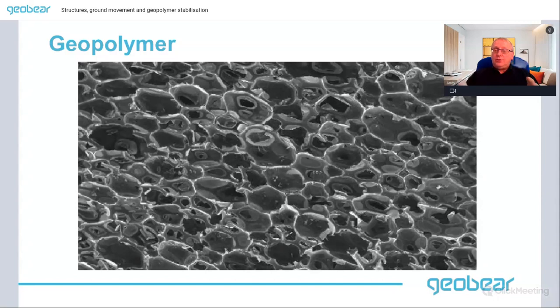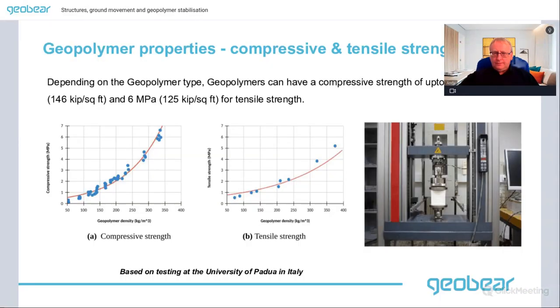And this shows you a cross-section of the reacted polymer, and you can see it has a foam-like structure. So the circles that you can see, that is the actual hardened resin, and inside these spheres is in fact carbon dioxide. So the chemical reaction releases carbon dioxide as a driving force of the expansion. So that's why it can expand. It's the generation of CO2 during the chemical reaction that's bound within the structure that causes the expansion. So that's how it works.